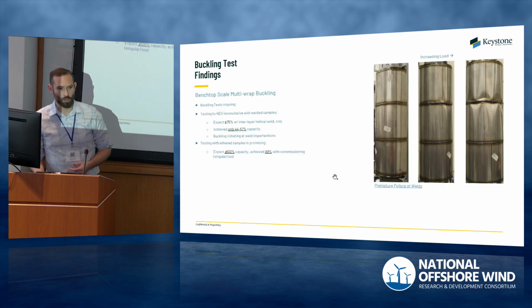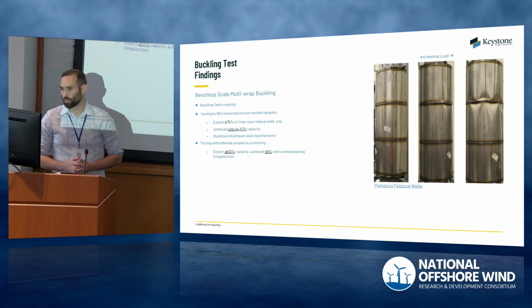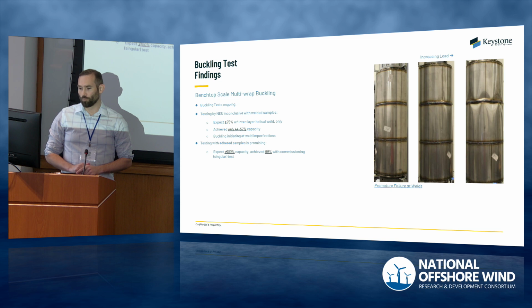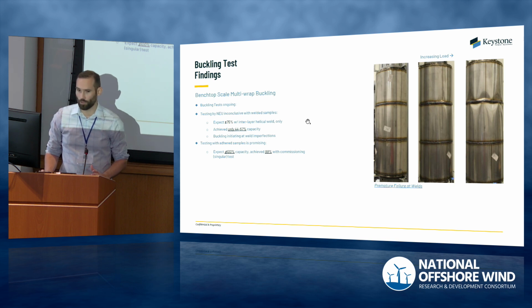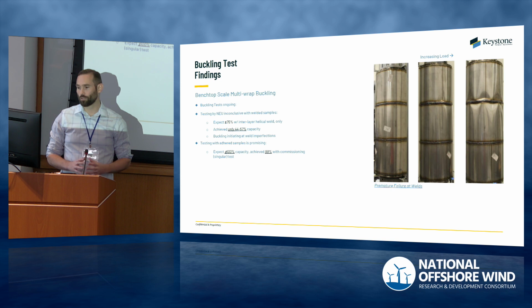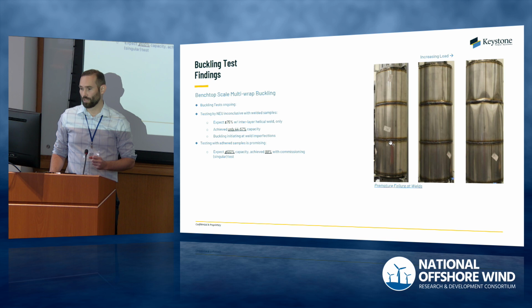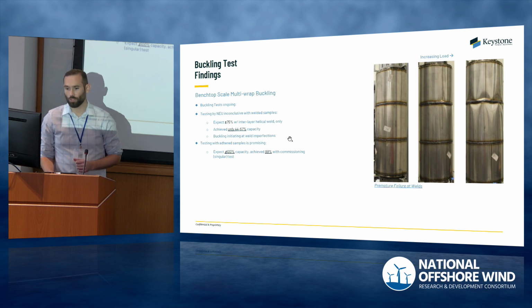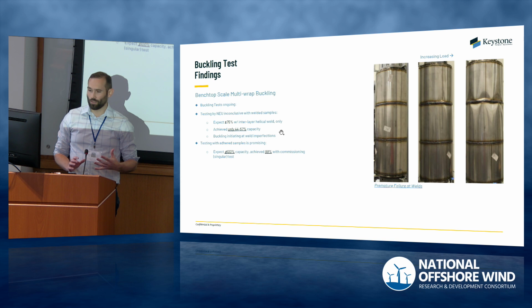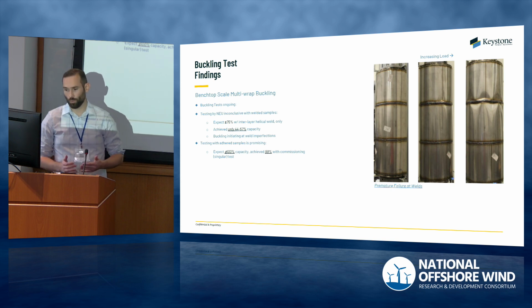And then Andy Myers over at Northeastern University has been doing some scaled down buckling testing for us. We have not seen the expected results, but I would say mostly this is all attributable to small scale fabrication issues. So you can see these relatively large weld beads, and you can even kind of see some of the flaws that exist just from the cold shrinkage of that weld. And so they did buckle prematurely. We've subsequently sort of redesigned these samples and used adhesives only, so as to avoid the small scale fabrication issues. And we are seeing this 100% buckling capacity as we would have expected.